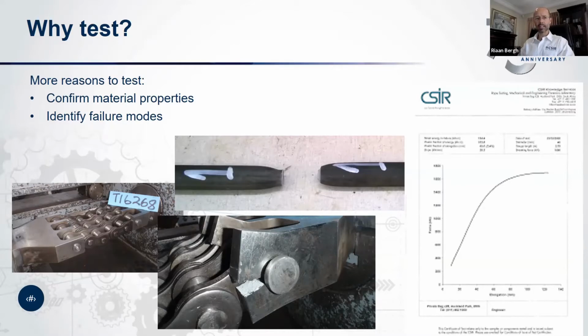And secondly, if we had insisted on a materials test certificate of the material that the test fixture was made of, we would have known ahead of time that this fixture was not at the required tensile grade. Unfortunately, we found that out after the fact in doing a bit of cause analysis, but it all could have been prevented had we insisted on a material test certificate for this material post heat treatment.